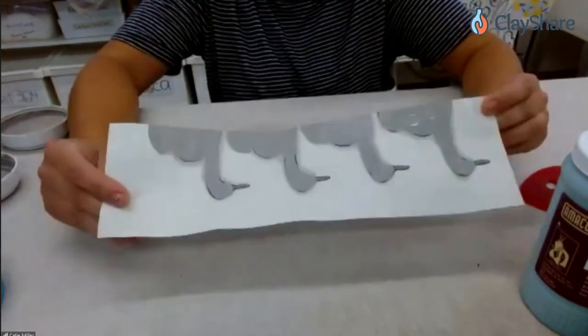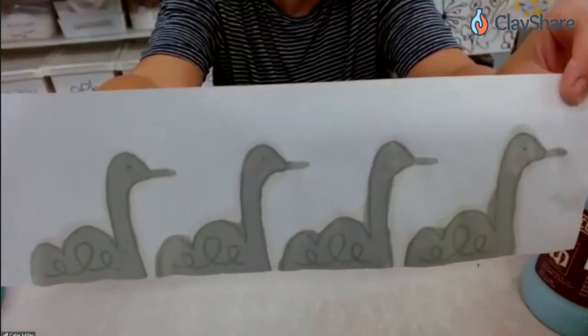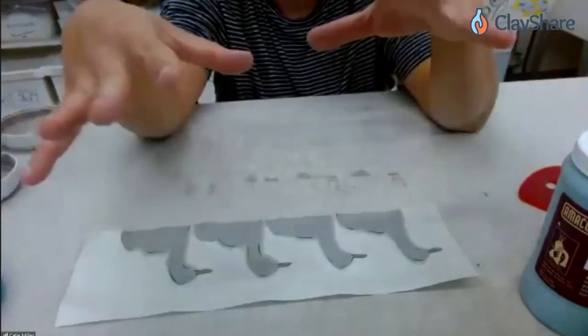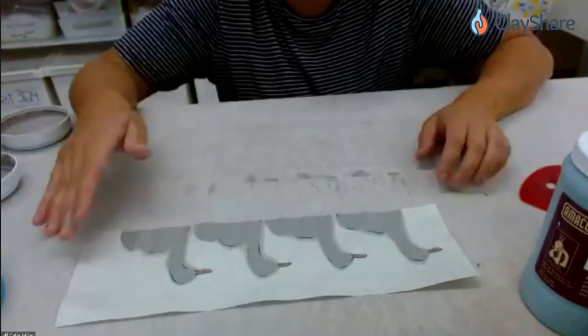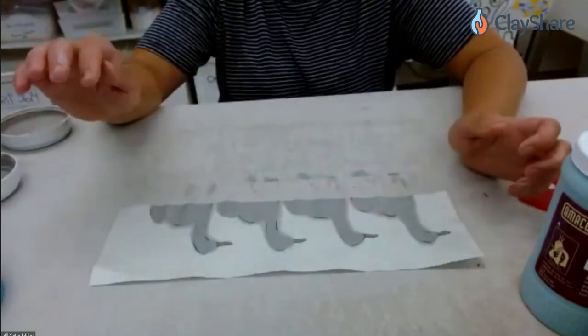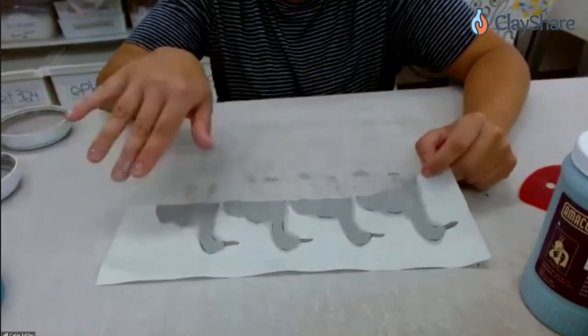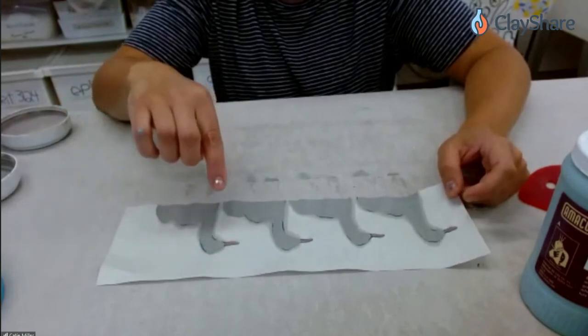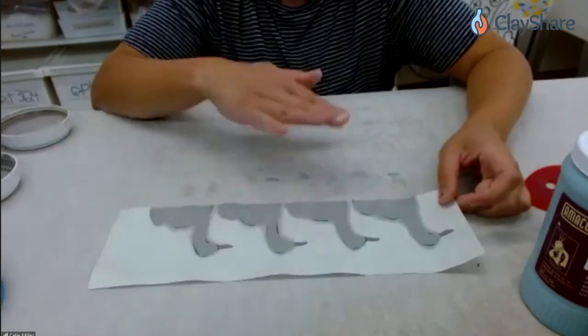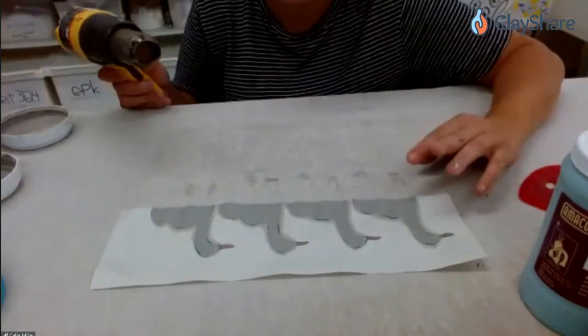Okay, so this is now all covered — you can see I've gone completely over the lines. If I flip it around the other way, you'll see you can still see those lines through. Now the paper is starting to get saturated and wet — you can see that halo of water. What the slip is doing right now is softening the underglaze so it will transfer and stick to the pot, as well as getting everything to kind of the same temperature. At this point it's a little bit shiny, a little bit wet. I don't want to keep layering colors because I will smear everything I've done. I've got white swans, a little touch of blue on their bellies, and their beaks and cheeks are this bright coral orange color. I'm just going to hit this with a heat gun so we can keep going.